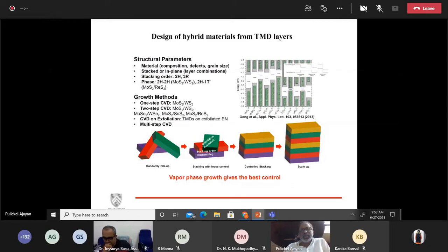Now, in addition to just the stacking of layers, especially when you stack layers, there is another interesting aspect that comes into the picture, and that is the rotational disorder. So, for example, graphite, you can either stack as Bernal stacking, which is essentially the real AB stacked graphite, or you can have rotationally disordered graphite, which we call turbostratic graphite. And the electronic properties are different in these. So this rotational disorder, or twisting, or essentially rotation, brings in a new aspect to these type of artificially stacked materials.